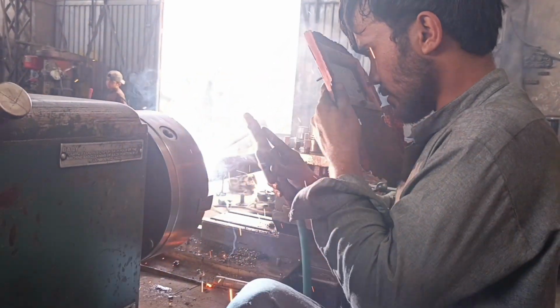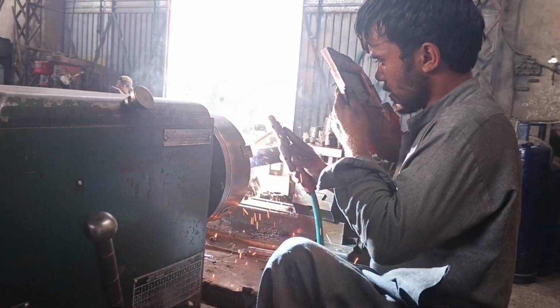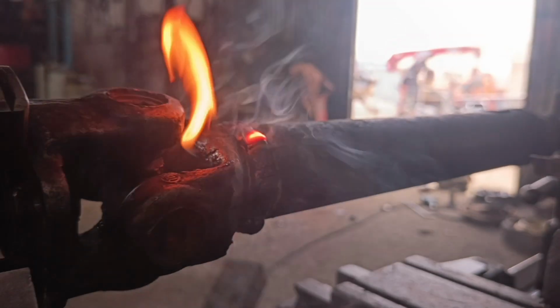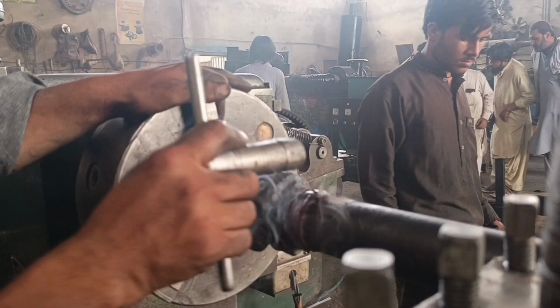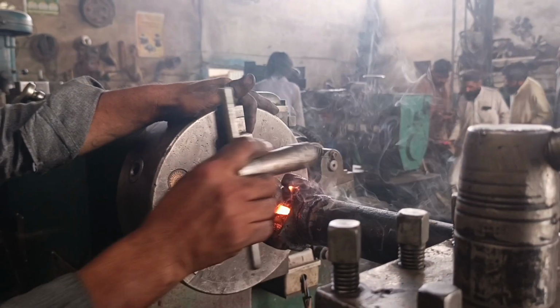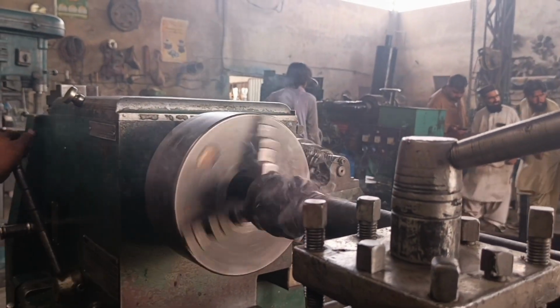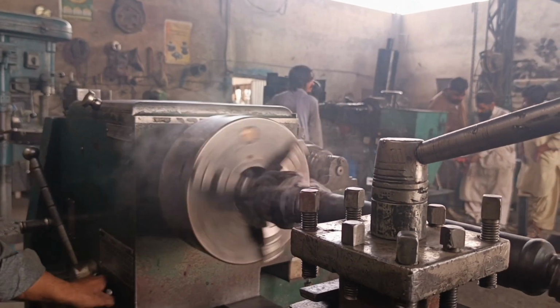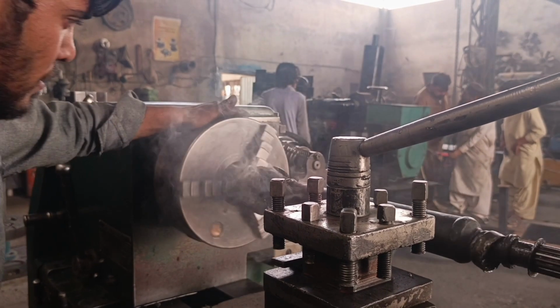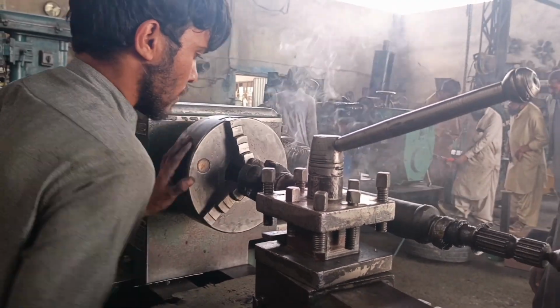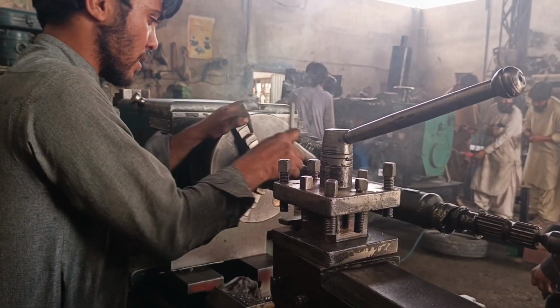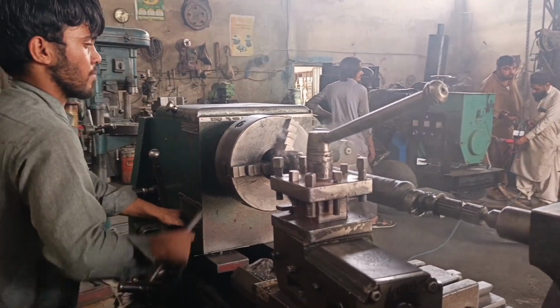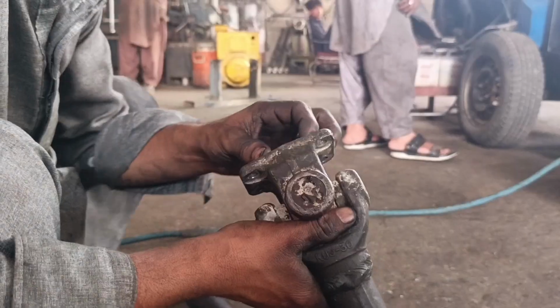The arc is started smoothly, and a stable weld pool is formed. The torch is moved around. The final welding now begins. The welding torch moves slowly around the circumference of the rotating shaft while maintaining a steady travel speed and a consistent arc length. The molten weld pool flows smoothly into the joint, creating complete fusion between the original shaft and the replacement section. Every movement is carefully controlled to produce a uniform weld bead with excellent penetration and maximum strength.